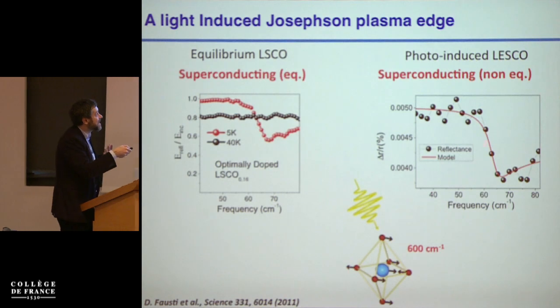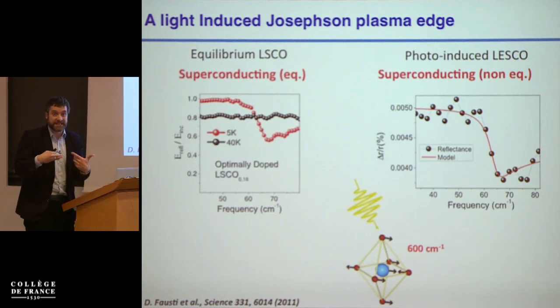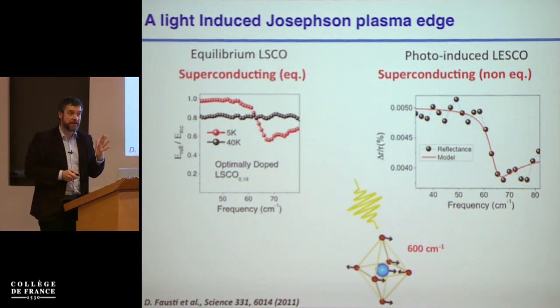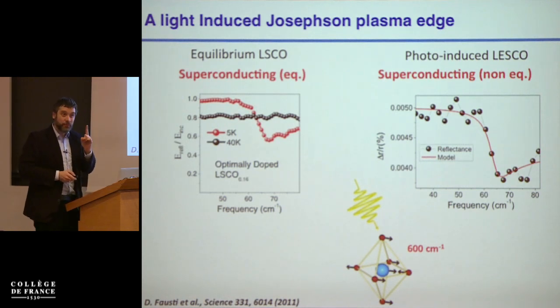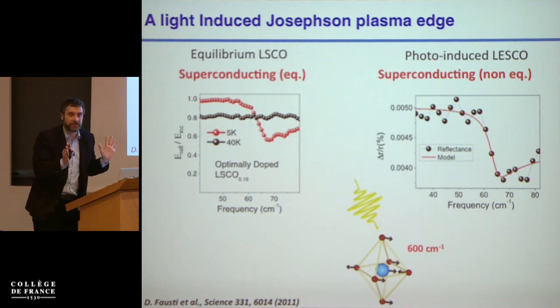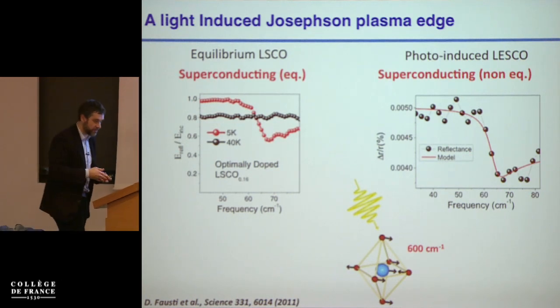The fact that I have a plasma edge at 2 terahertz is indicative of the fact that I have very high mobility transport perpendicular to the planes at a density which is exactly the same as the density of Cooper pairs in the optimally doped compounds. So this is what this experiment shows.